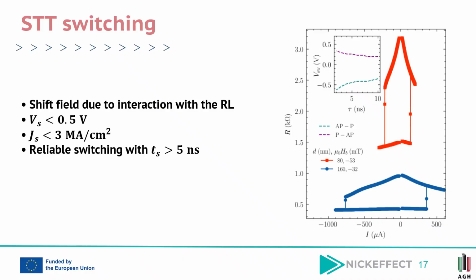of the free layer. A noticeable shift of the switching loop is observed due to the interaction between the free layer and the reference layer system. Nevertheless, reliable bipolar switching is maintained over a broad current range. The optimized MTJ devices exhibit switching voltages below 0.5 volt and switching current densities below 3 megaamps per centimeter squared, which are highly favorable for low-power STT MRAM application.